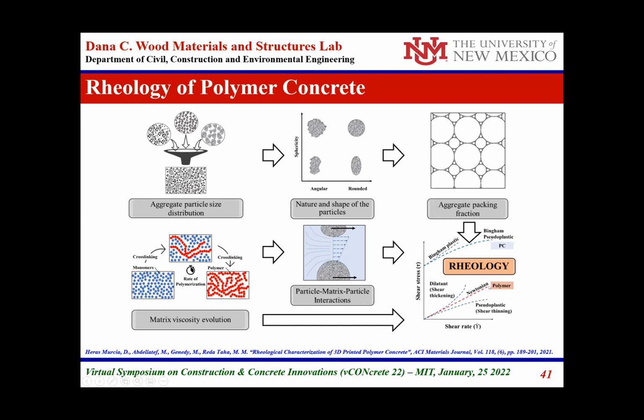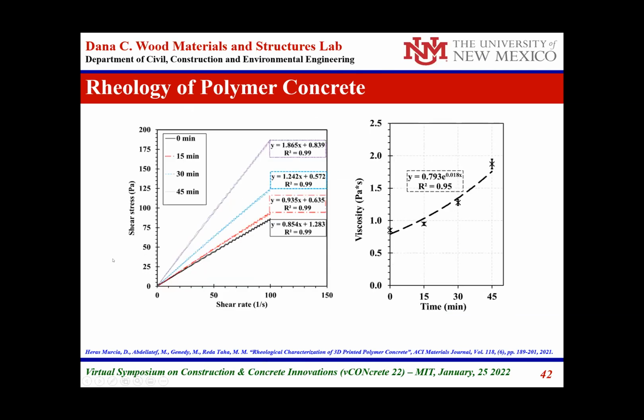The rheology of the polymer is a typical Newtonian relationship between shear rate and shear stress, while the polymer concrete follows what we call a Bingham pseudoplastic model. This is the measurement for the polymer, and you can see it is very linear—that's the change in viscosity of the polymer with time.